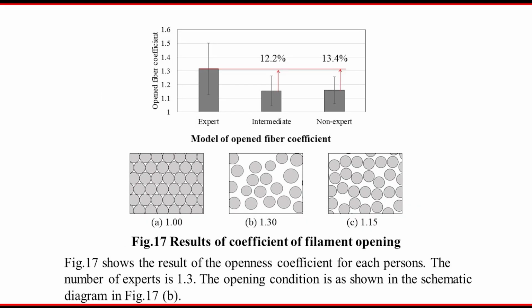So this is the opening fiber coefficient, Expert and intermediate part, non-Expert. This data shows that in the case of the Expert, the fiber filament opened and existed individually in the matrix. The Expert coefficient is 1.3 and the intermediate person is 1.15.